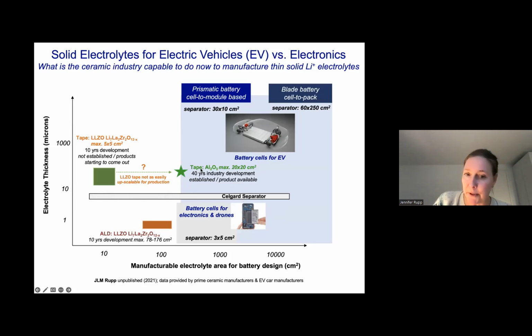In classic ceramic production, if you look over the last 50 years, alumina took about 40 years to get a 20 by 20 square centimeter crack-free tape. Yeah, and that's the effort of industry. Currently, I would say that the lithium garnet electrolytes that I know of have been upscaled as tapes to about 5 by 5 square centimeters by manufacturers, or are currently in designs of that. But going from here to full battery integration is still some way.